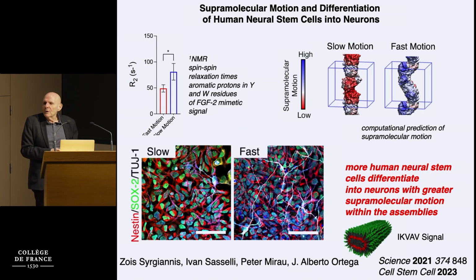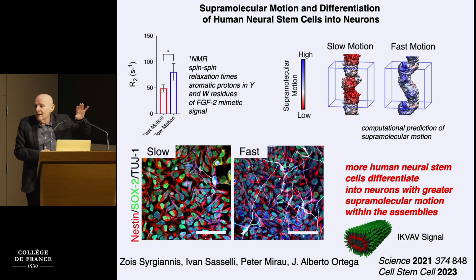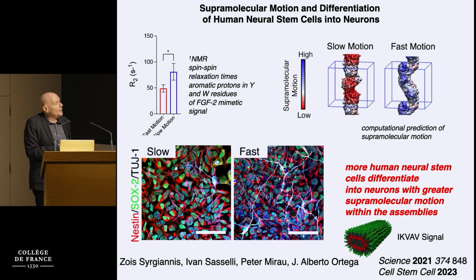And it was really interesting to find, which I think is remarkable, that this tiny change of that tetrapeptide, without touching the bioactive signal, right, the disease-curing sequence, basically when you put human neural stem cells on top, you see after a week or so lots of neurons here in white appearing on this carpet of lots of red and green, which are these markers for stemness.